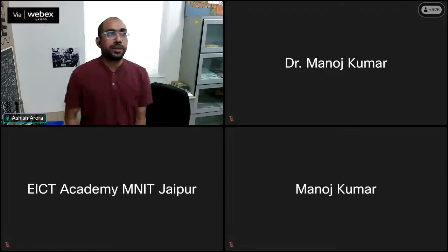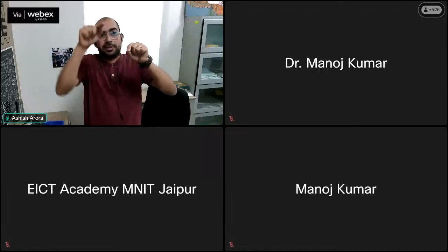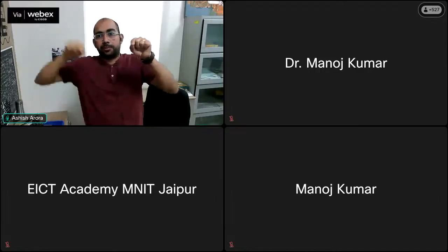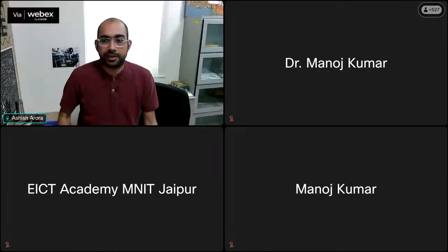So one has this differential spectroscopy, which is very sensitive to the number of layers. In fact, if we measure the spectra as a function of layer thickness, we find that the difference spectra, for example for a monolayer, look like this, for bilayer it's like double, for trilayer a bit more, for four layers a bit more. So there are large differences between different layer thicknesses in all these spectra. So that is useful. Definitely.